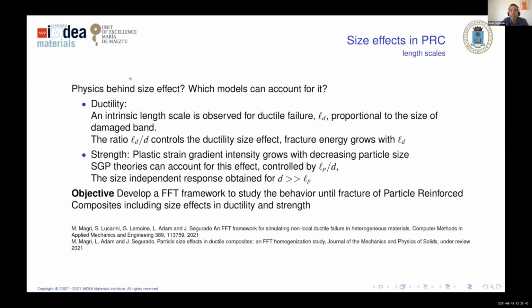In the case of ductility, we have to think in terms of an intrinsic length scale. This intrinsic length scale, which in the case of the smaller length scale was the Burgers vector, in this case is the size of the damage band. So in ductile failure, we observe a band of damage. So we don't have a localized crack. We have a damage band that introduces an intrinsic characteristic length. And then the ratio between the characteristic band of the damage and the size of the particles is the one that drives the size effect in terms of fracture.